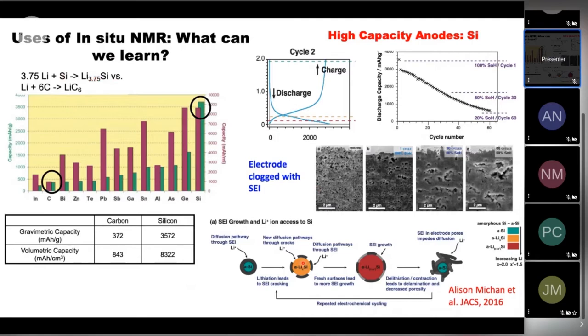The problem with it, though, is that the expansion and contraction of the silicon exposes new surfaces that can react with the electrolyte, and you form electrodes that end up being clogged by something called the SEI, or the solid electrolyte interphase. And ultimately, this then results in a decrease in capacity. And also, you can imagine that this would increase the impedance, or the difficulty of the lithium ions getting through this thick mess. So a lot of work is being done globally to try and improve the functioning of silicon in batteries.